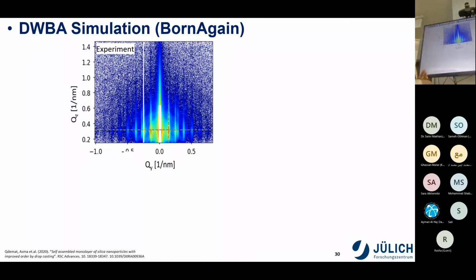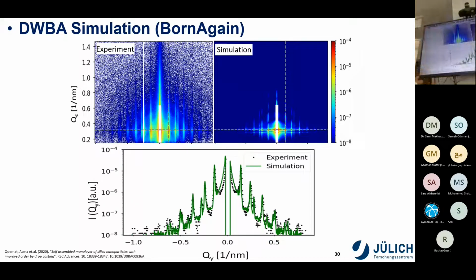Further, the GISAXS pattern obtained for this monolayer, I tried to simulate it using BornAgain software based on the distorted-wave Born approximation. BornAgain is free software that anyone can use for fitting and simulation of monolayer and multilayer systems, and it can handle GISAXS or GISANS measurements. This software uses the physics of the distorted-wave Born approximation, and to reproduce or fit the system I assumed a monolayer of nanoparticles in a 2D hexagonal lattice, and we end up with a simulation which is quite close to the experimental data.